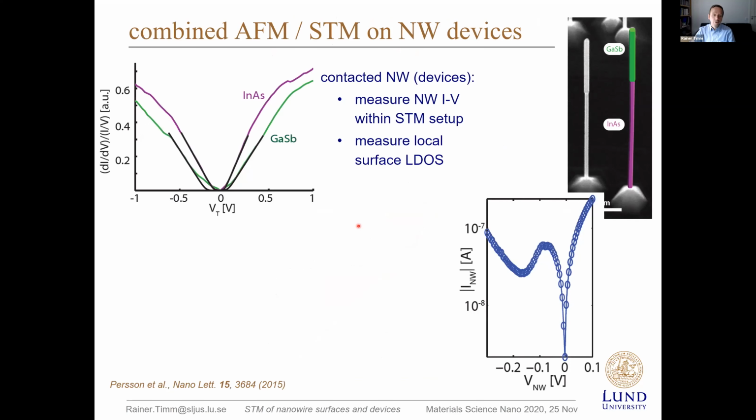But if we now switch to STM mode, once we are on top of our nanowire, we know that we are on a conductive ground, so we can switch to STM mode, take STS spectra, and we see, oh, our spectra more or less overlap here in energy. So this electronic footprint that we see at the surface would never correspond to a tunnel barrier as we have here. Again, the surface is different than the bulk inside.